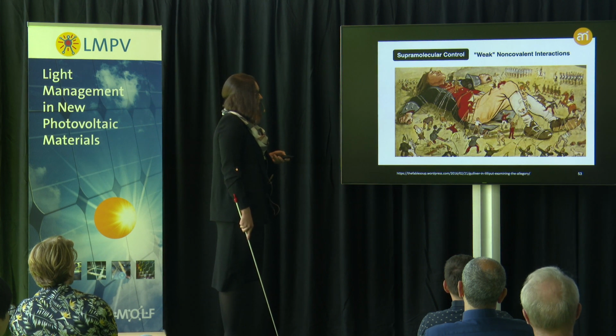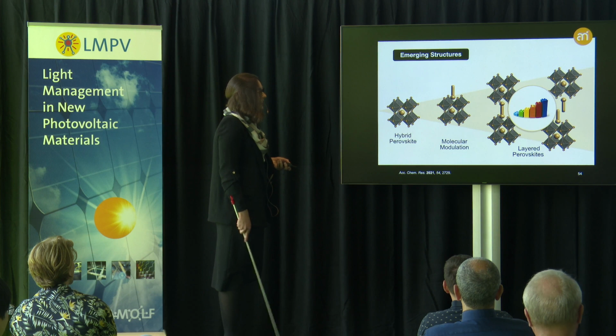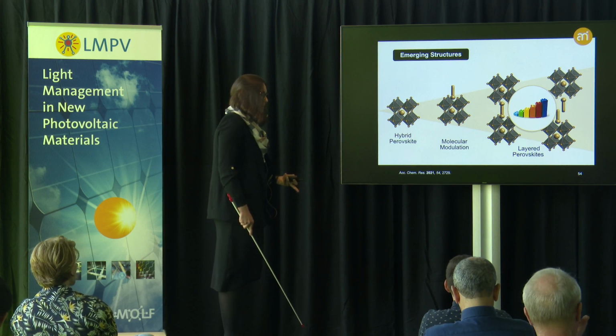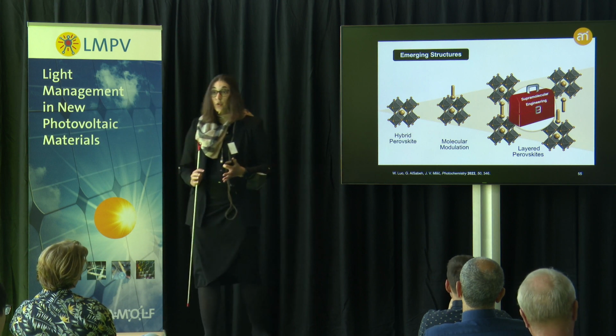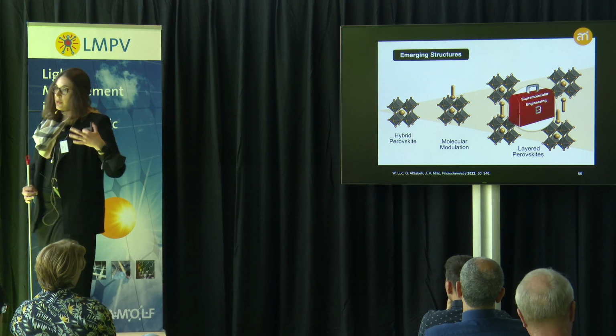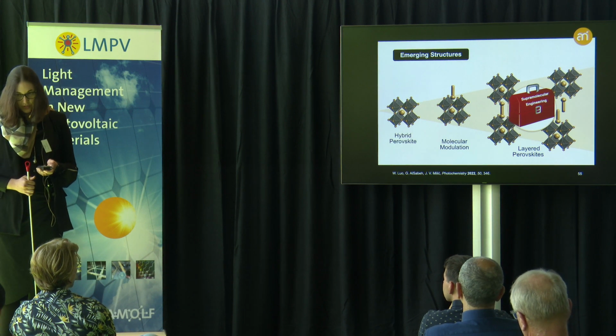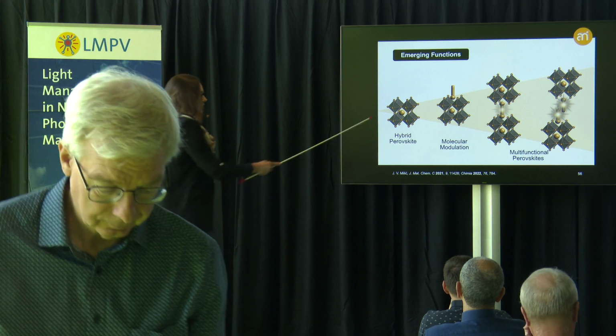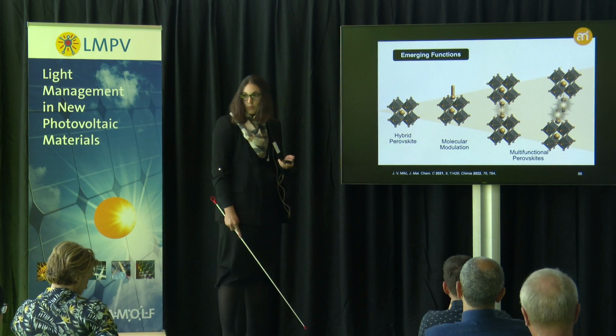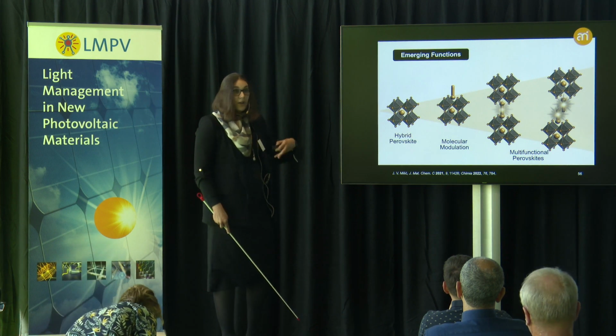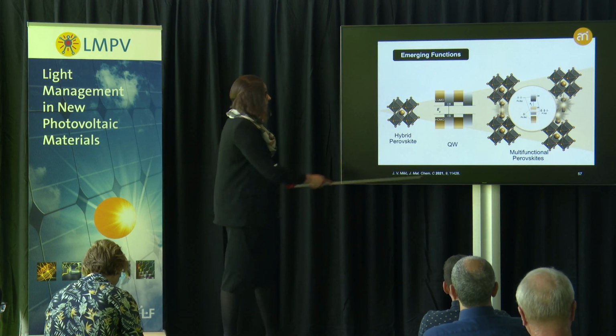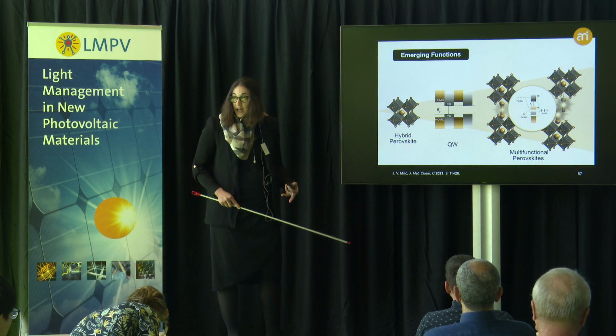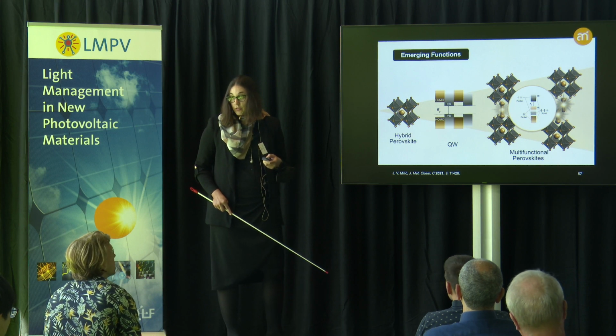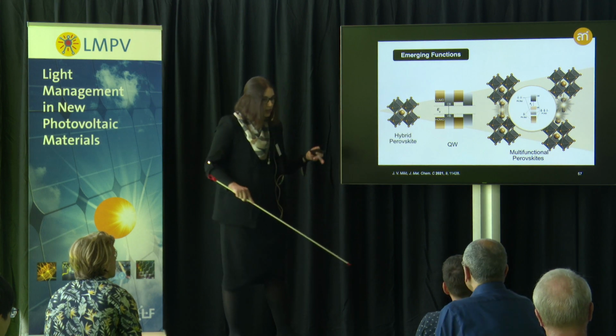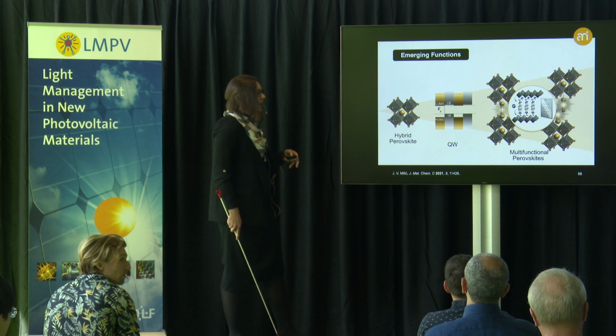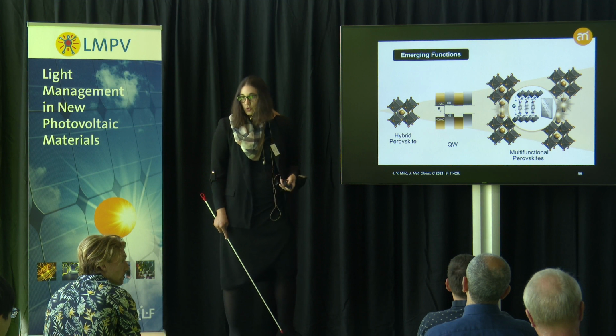Now with that in mind, this also provides the possibility to not only control these assemblies, but to rely on the powerful features of this toolbox to not only address the pressing challenges, but also take a step further in enhancing the functionalities of these systems, which involves, for instance, introducing additional functions within these organic moieties, in the form of a variety of different functionalities of the organic components that enables tailoring these optoelectronic properties that are primarily defined by, as I mentioned, the metal halide orbital overlaps, and which can be changed even in terms of their basic band gap and other characteristics by enabling the organic component to really contribute to some of these features,